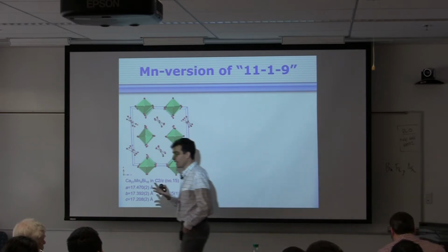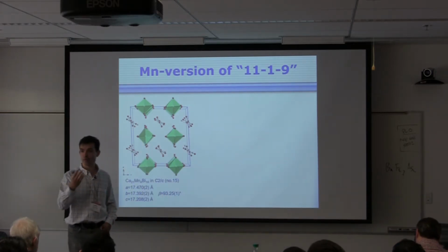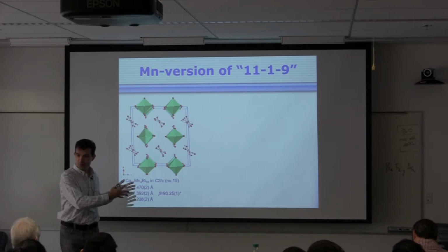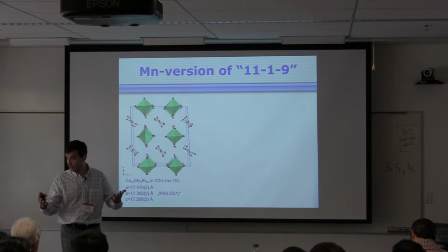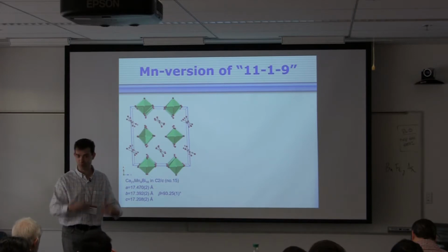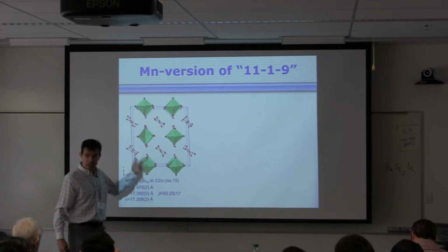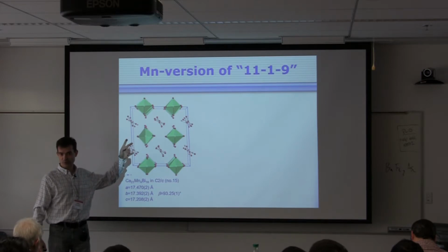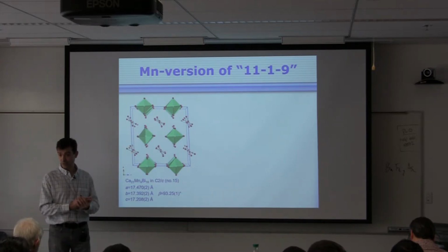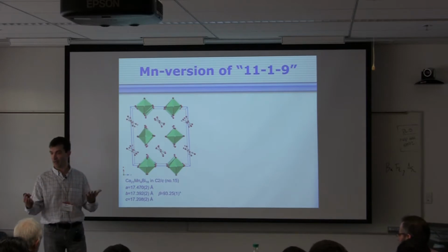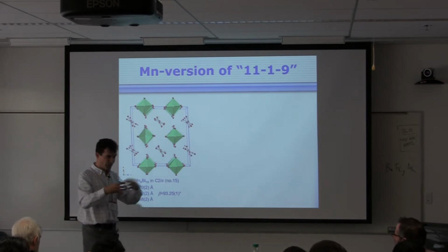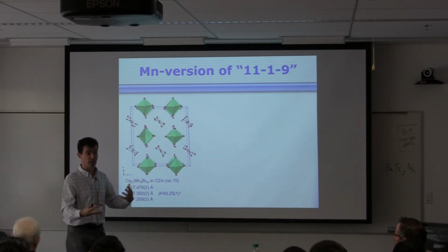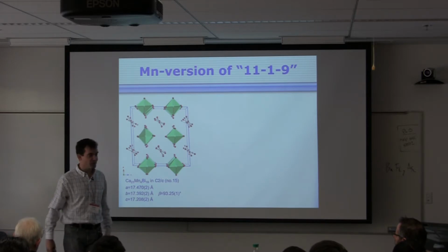The problem was that the compound was very unstable. My motivation was to use this small-gap semiconductor for thermoelectric applications. Thermoelectrics requires high temperature because we wanted to harvest energy, not use it for cooling. So with a graduate student we decided to use d metals, because transition metals have higher melting points. We figured that indium, being this soft and squishy thing with a low melting point, is maybe the reason the compound falls apart at 200 degrees C.